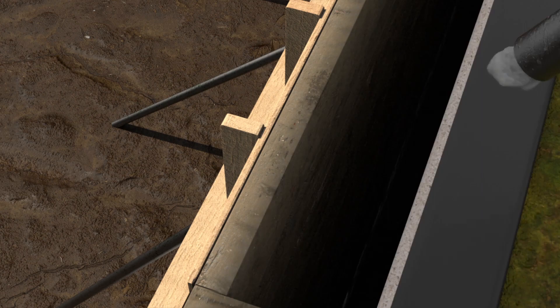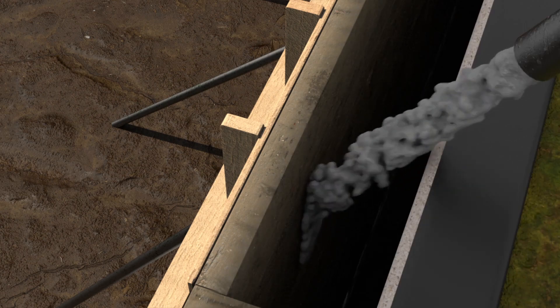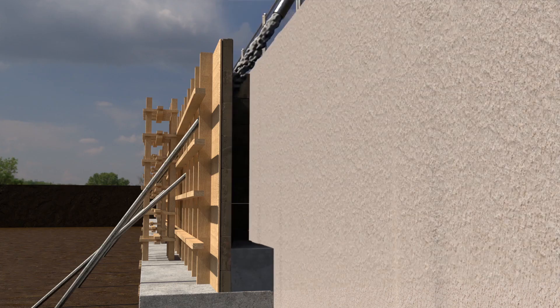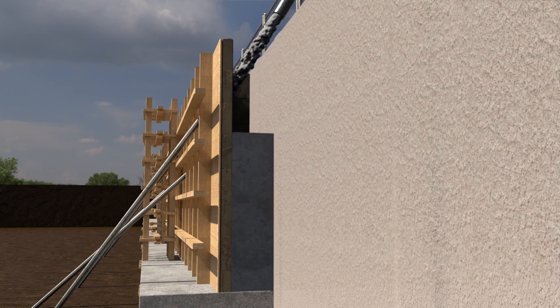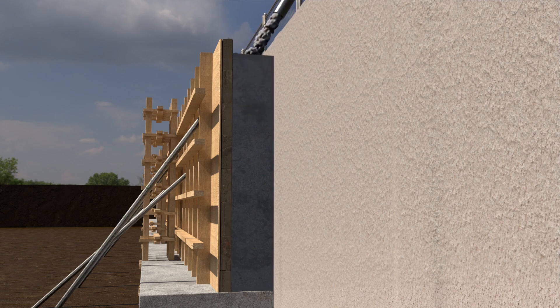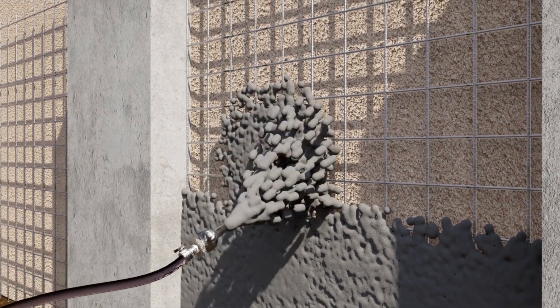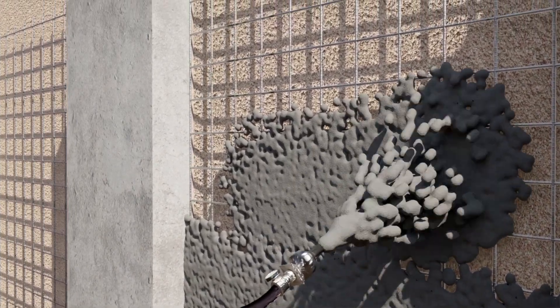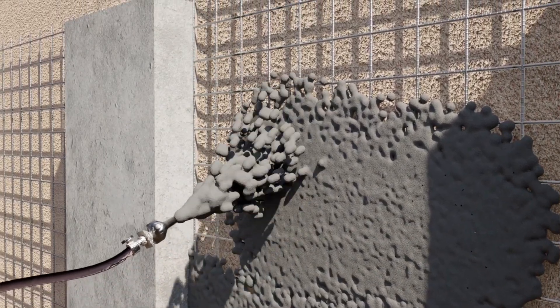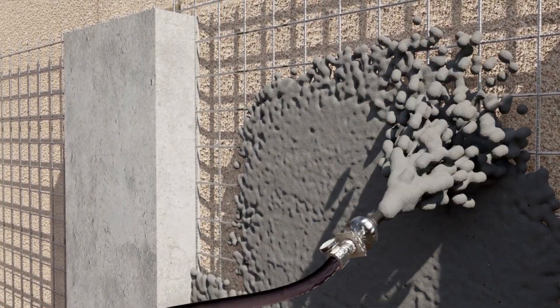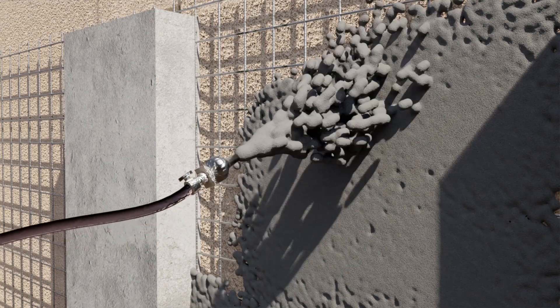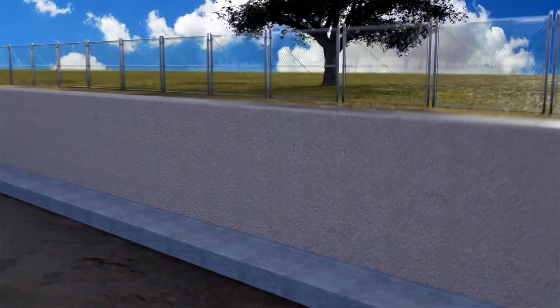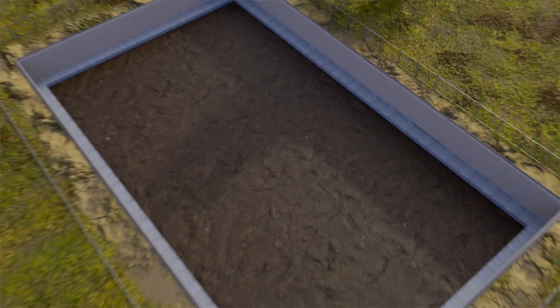If the structural wall is poured in place, the concrete should not be dropped from higher than 4 feet (1.2 meters), and the concrete should be forced towards the formwork and not the membrane. If the structural wall is shotcrete, the spray should be blown in at an upward direction in 4 foot (1.2 meter) lifts so as not to lodge between the seam lap.